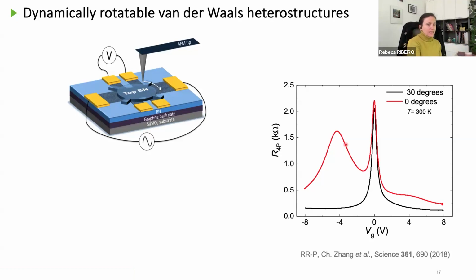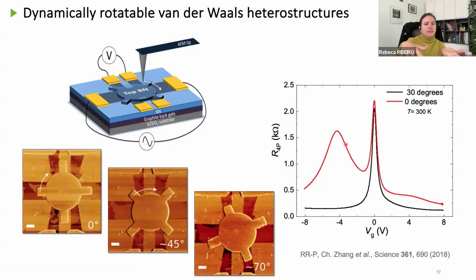So the way we do this is we predefine our device. Here, what you have is boron nitride on the bottom. Then you have a whole bar made of graphene, that is the dark side here. And on top of it, we're going to deposit a layer of boron nitride, but this layer of boron nitride is in fact pre-shaped in a way that we can rotate it. And you can see here, for example, the motion of these, we call them handles. These handles, we rotate continuously.